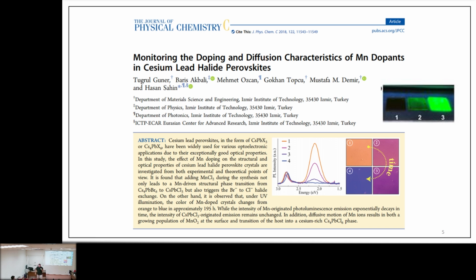And another calculation was molecular dynamics calculation. I inserted manganese atoms inside the cesium lead chloride and bromide. Then I started heating up the material up to the room temperature. Then I noticed that manganese atoms, they don't stay in a certain place. They are very small, and they diffuse easily, and they don't prefer to be bonded in the material. And so we saw it from molecular dynamics calculations, and in reality, actually inside there were no manganese atoms. We just saw manganese oxides at the surface.